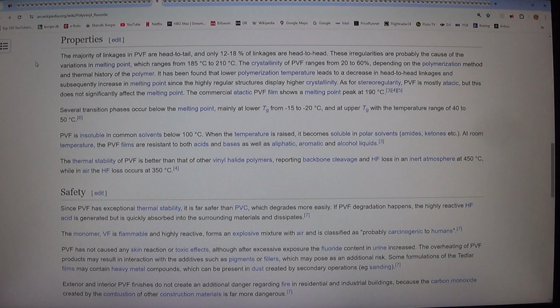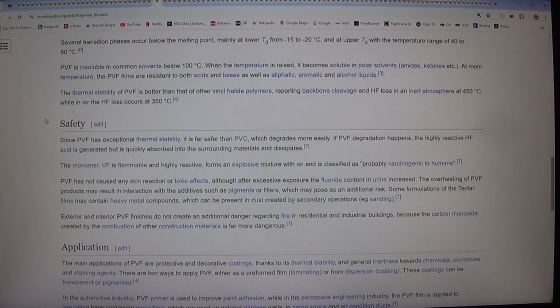It has been found that lower polymerization temperature leads to a decrease in head-to-head linkages and subsequently an increase in melting point, since the highly regular structures display higher crystallinity. As for stereoregularity, PVF is mostly atactic, but this does not significantly affect the melting point. The commercial atactic PVF film shows a melting point peak at 190 degrees Celsius. Several transition phases occur below the melting point, mainly at lower Tg from -15 to -20 degrees C, and at upper Tg with the temperature range of 40 to 50 degrees Celsius.